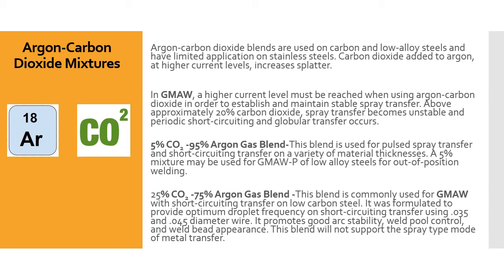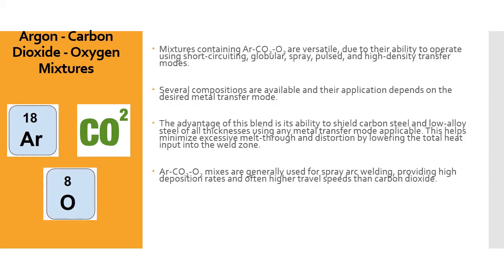Argon-carbon dioxide-oxygen tri-mixtures are generally used for spray arc welding, providing high deposition rates and often higher travel speeds than carbon dioxide alone. These three-gas mixtures are versatile — they can operate in short-circuiting, globular, spray, pulse, and high-density transfer modes. There are a bunch of different compositions available, and they work well for carbon steel and low-alloy steels of various thicknesses. These tri-mixes offer a lot of advantages and are worth looking into.